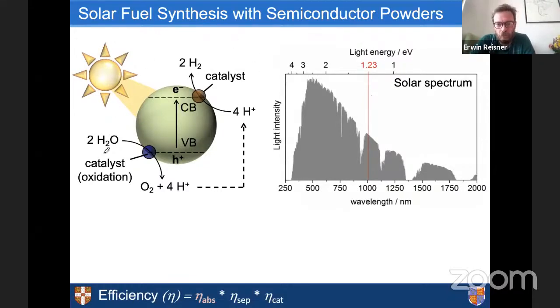And of course, in this case, what I just mentioned before, we have the thermodynamic requirement. If we think about a single light absorber, we always need more energy than the 1.23 electron volts that you need for the water splitting reaction. Taking into account also some kinetic losses, you look at much more like 1.6, 1.7 electron volts as a practical minimum.